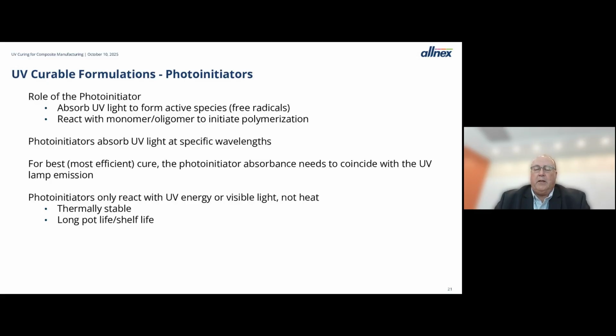So UV lamps, while they do give out energy across the UV spectrum, that energy is concentrated in some areas more than others, and you want to choose photoinitiators that make the best use of the available energy. The last part is photoinitiators are pretty thermally stable. So they only react with UV energy, not heat. And this is part of the reason that UV systems have such a long pot life or shelf life.